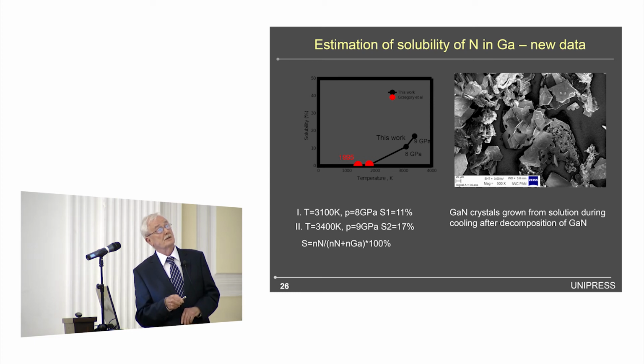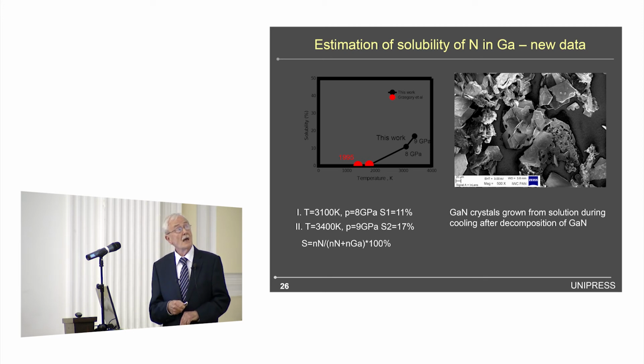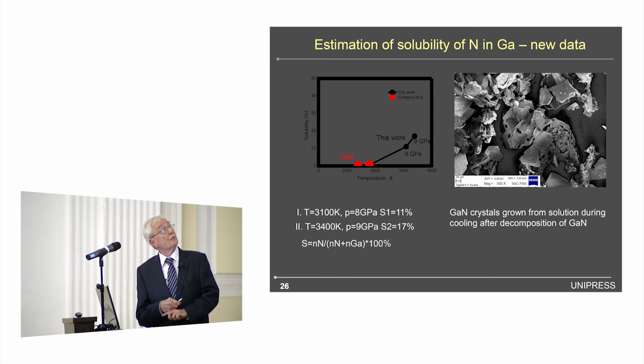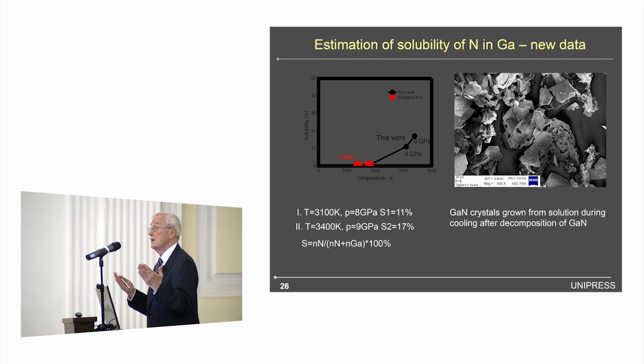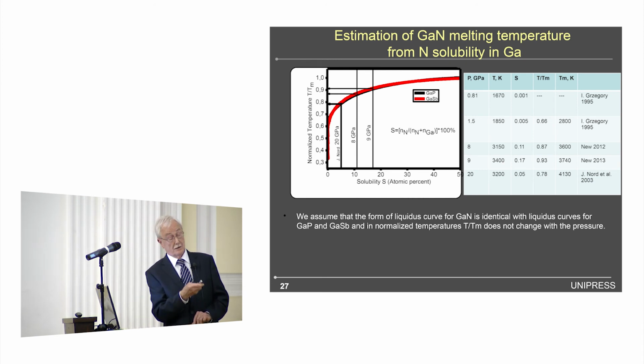We have 2 points. We have solubility for 8 gigapascals and 9 gigapascals, and corresponding temperatures are 3,100 and 3,400. From this data, from solubility, if we know the liquidus curve, we can very easily find the melting temperature. And this is shown here.